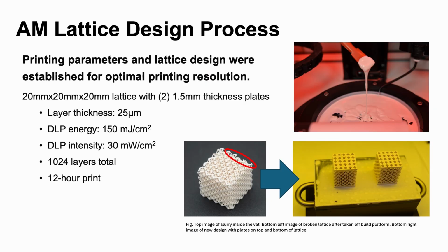So we originally designed the lattices to be 20 by 20 by 20 millimeters. However, as seen in this photo, the struts were damaged when removed from the build platform. So then we decided to create the lattices with a top and bottom plate that was 1.5 millimeters thick. We made these open areas to help them with sintering, and then we set the layer thickness to 25 microns, which is the highest in the Z resolution.